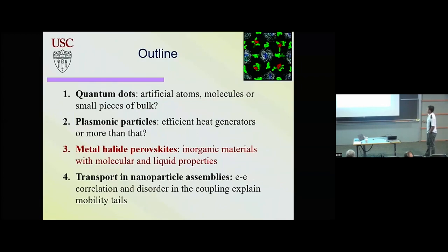So now I'll talk a little bit about perovskites, which is a very interesting material because it combines features of organic matter, inorganic matter, and even liquids to some extent. Of course, the motivation is that they're very efficient. You have very bright luminescence in quantum dots. For solar cells, you have very high efficiency, but the physics of the material is also very interesting. So what's the material? You have an inorganic lattice, lead iodide, for example, and this inorganic lattice creates a continuous channel for transport. So that's why they conduct very well compared to organic materials, for example.